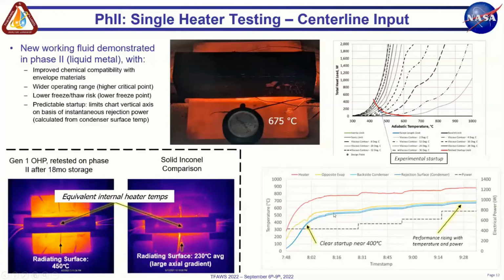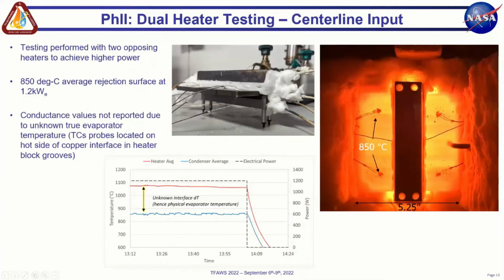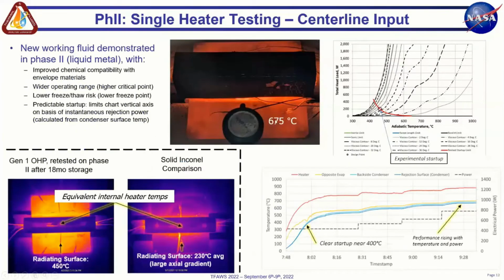So that closes up these series, tighten up, showing improved performance actually as you go up in temperature and power. So we're transporting more heat with lower gradient. So the quotient there is showing steadily improving thermal conductance. Well, we wanted to go even hotter. Here we're getting up to 675 with the condenser. We wanted to go hotter.